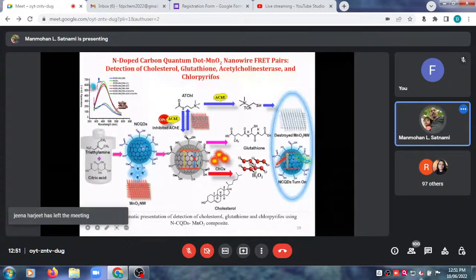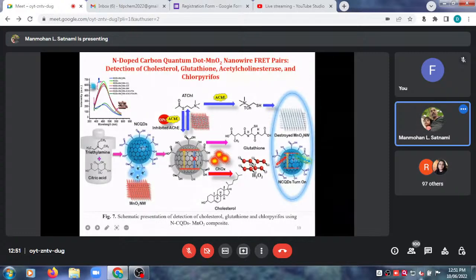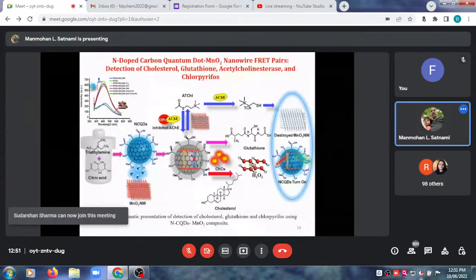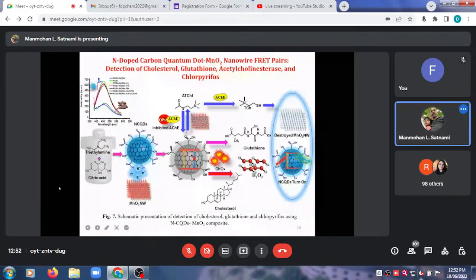See, we prepared carbon quantum dot using citric acid and triethylamine as precursors. So triethylamine we use as a nitrogen source, and citric acid as a carbon source, and we put these two compounds in the hydrothermal autoclave and heated it at 180 degrees centigrade, I think, for 10 hours. So after cooling, we took out the content and we dialyzed it through the dialysis membrane, so that any kind of impurities or bigger size carbon quantum dots can be filtered out.